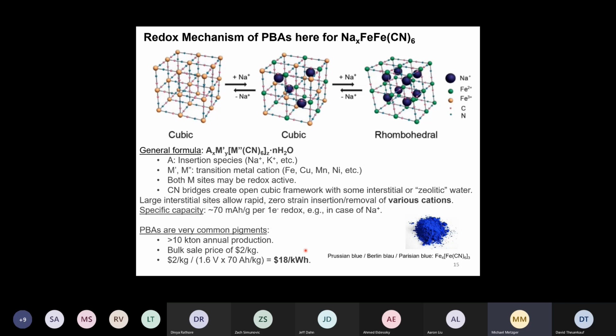Yeah. But now, from this fairly cheap material, you can, back of the envelope, calculate cost per energy on a materials level. So, if we take the $2 per kilogram and we divide it by the energy that we can get out of this material, which would be the 70 milliamp hours per gram, or amp hours per kilogram, from here. And then if we assume we had a cell that has an average voltage of 1.6 volts, you multiply those two, you get the energy, then this would amount to roughly $18 per kilowatt hour.